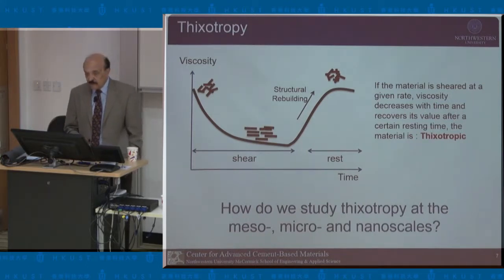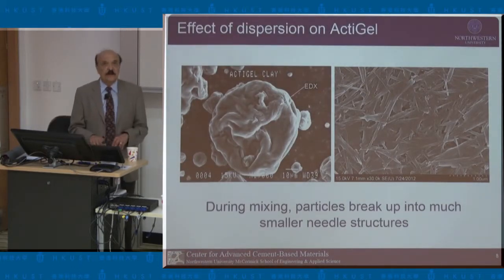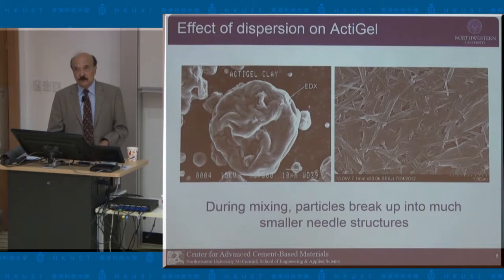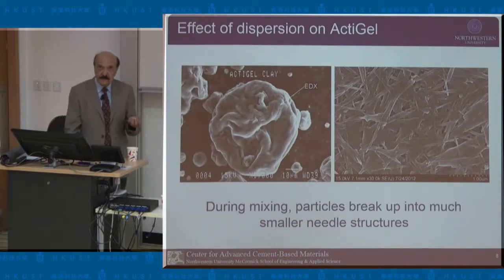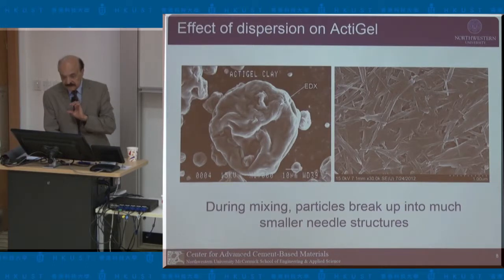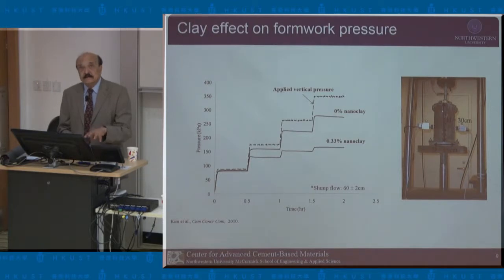So, as I mentioned, one of the ways we have found that we can manipulate thixotropy is by adding a small amount of nanoparticle. These are commercially called Actigel, and they are magnesium aluminosilicate. What they are is you have a clay, and they are exfoliated, and so they are stable at nanoscale. So just to show you one way